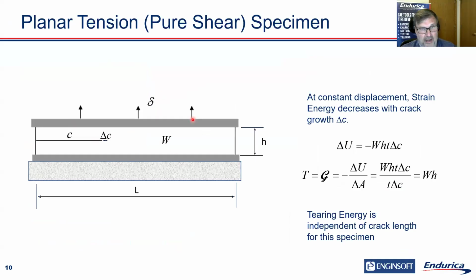And we can easily derive the value of tearing energy for this specimen by considering the fact that we're loaded in the vertical direction. We're going to have this homogeneous area of strain energy density here, and it's going to be unloaded here. So as the crack grows by an amount delta C, the volume of this area that's loaded with the strain energy density W is going to go down by this volume dictated by delta C. So that volume is delta C times the thickness of the specimen times the height H.